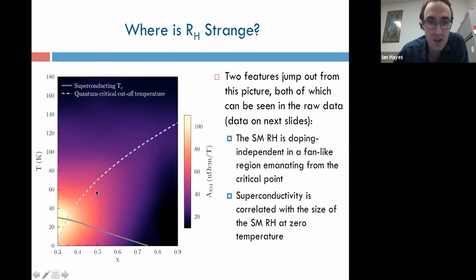So this looks very much like there's some detuning energy in the system that is getting stronger as we move towards higher phosphorus doping, such that if temperature is larger than that detuning energy, you simply get the same effect, independent of what your actual doping value is. So this is striking. There aren't too many experimental observations that paint the fan quite this clearly. So this is fairly striking evidence in favor of the idea that this effect is coming from the influence of the nearby ordered phase.